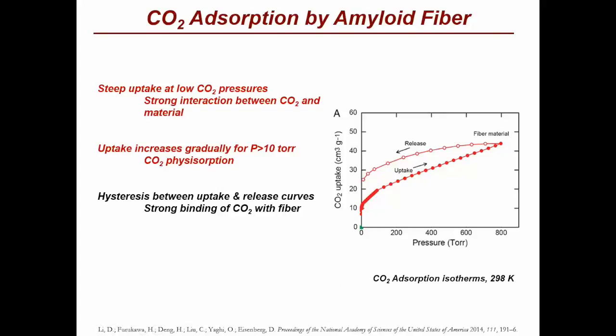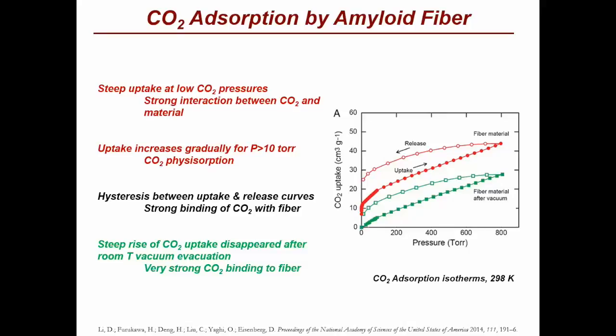with the fiber materials. This material was then evacuated at room temperature under vacuum, and the CO2 adsorption was measured again. Now we can see that the steep part of the uptake has disappeared, which indicates again the strong binding of CO2 with the fiber materials, and that this room temperature vacuum evacuation was not enough to remove all the CO2.